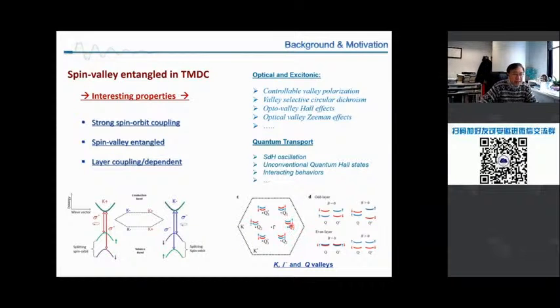All right, and those spin states, I say this is valley entangled. That means, for example, you have an even layer of material, and then the spin up and spin down are degenerate, occupying Q, and the total degeneracy is 12. So once you apply a magnetic field, spin up and spin down shift, and then the lower energy states Q and Q prime, the total degeneracy is 6. But if you make an odd layer, monolayer or trilayer, this spin up and spin down are already lifted. So the degeneracy is already 6. And once you apply a magnetic field, the spin down and spin up shift, and basically you only detect one of the spin states, and that degeneracy is just 3. It's just 3. So that is the interesting state.